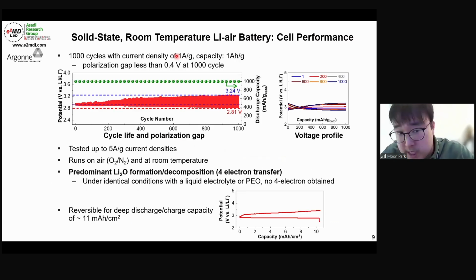And this is the battery performance with the CPE-based solid electrolyte, and it performed 1,000 cycles. At the end of the 1,000 cycles, the discharge voltage is still high at 2.81 volts, and the charge potential is 3.24 volts, having around 0.4 volt of overpotential, which indicates a very high energy efficiency. And it also showed the deep discharge of 11 milliampere hour per square centimeter, which has a high potential for being used in heavy duty vehicles.